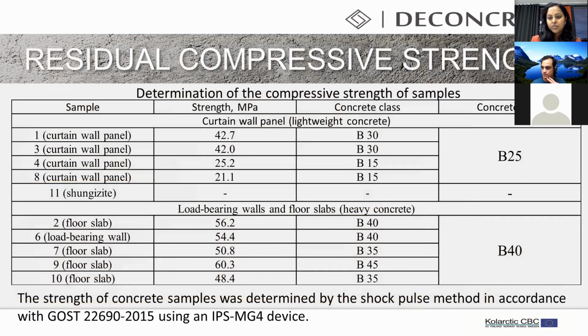So we determined the residual compressive strength of the different samples. Lightweight concrete, the curtain wall panel, has a strength of about 20 to 40 megapascals, concrete class B25. And heavy concrete has a residual compressive strength of about 40 to 60. It's very good actually, concrete class about B40. And this sample has very high residual compressive strength.